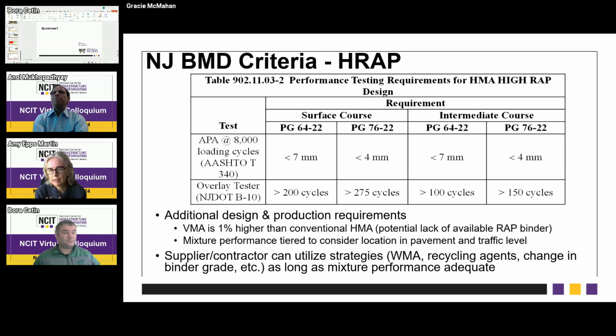So in the New Jersey part of the project, the supplier or the contractor can utilize different cracking strategies, including warm mix asphalt additives, recycling agents, changes or substitute binder grades. They can do all kinds of different things to offset the effects of the stiff, aged RAP materials that are being added at higher and higher contents, as long as they meet these cracking and rutting criteria.